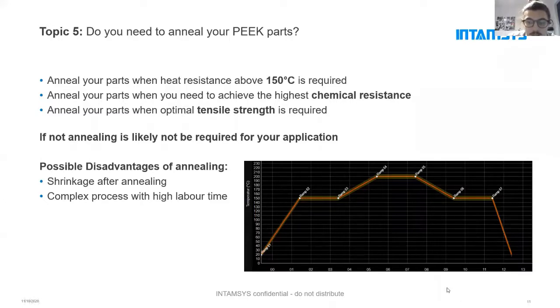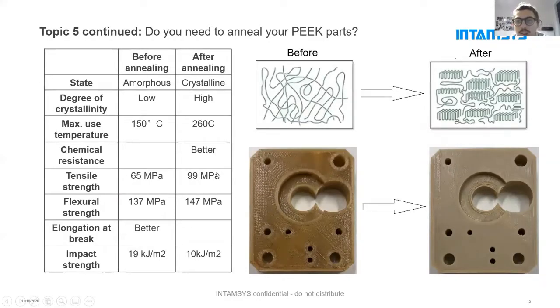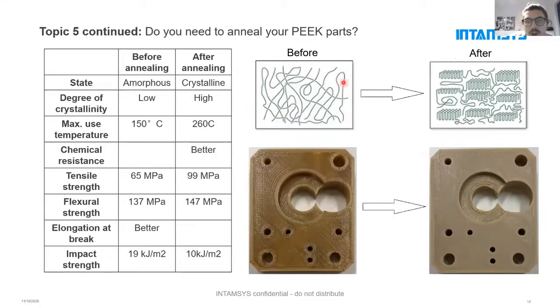One thing is quite important there, and this is something that you see. I say, okay, higher than 150, high tensile strength. Let's see on the next page what happens within crystallization or within annealing. So what you could see here is the structure, how it looks when it's purely amorphous. There's still slight crystallization, but this is more or less a very amorphous part. So you have a very open, chaotic structure. When you anneal it, the structure sorts, gets more dense, and this is also the reason why the parts shrink within annealing. You still see some amorphous structure, and this is related to the semi-crystallinity of PEEK. So there will not every time be only one big block of crystallized structures.